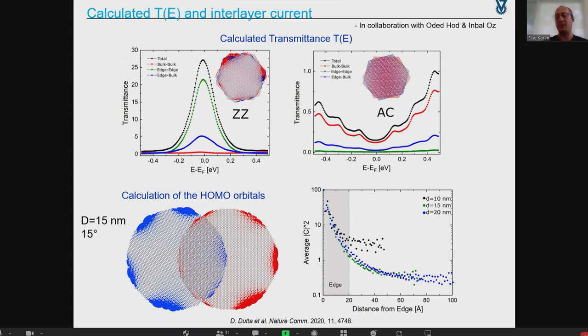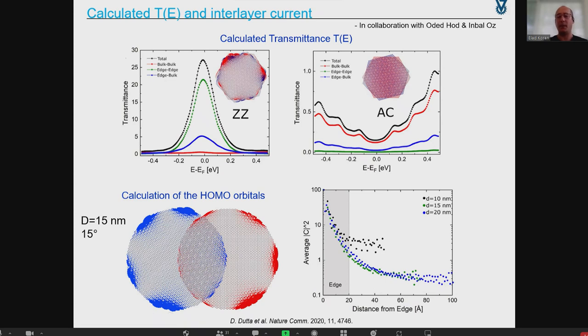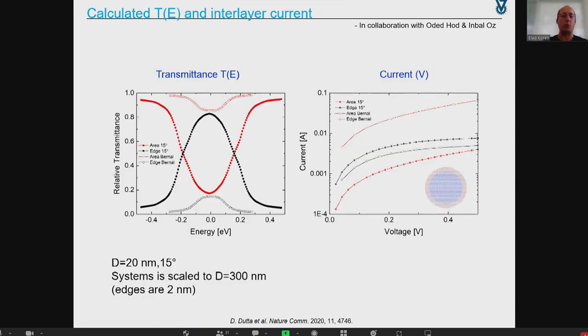This tells us we can use these wave function characteristics to explain larger flakes by simply scaling up geometrically. The second important point is that we can associate the main edge transport with just the first two nanometers around the circumference — we get almost two orders of magnitude decay across the first two nanometers. The theoretical approach is to separate the transport contribution of the first two nanometers around the circumference from the bulk regime and compare them, scaling in a simple geometrical manner.